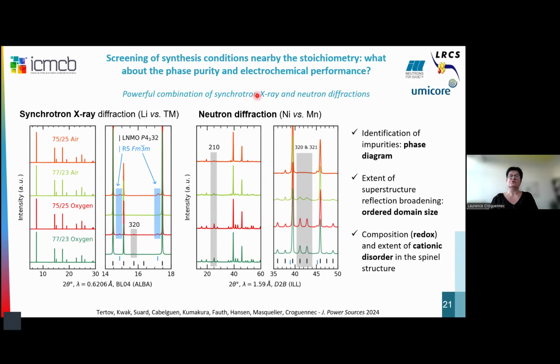So now if we jump to neutrons, the benefit of neutrons is also really that we can distinguish nickel and manganese in these materials. And so we are able to distinguish what I called at the beginning the disordered structure, with a statistical occupancy of the octahedral site, and the ordered one, with one site for one transition metal. You can see here in red, in gray, I would say, the order superstructure lines. And you can see that for all of them, we can see the superstructure lines, whatever the synthesis conditions. I recall that the second thermal treatment was done at 725 degrees, so in the domain of stability of the ordered phase.